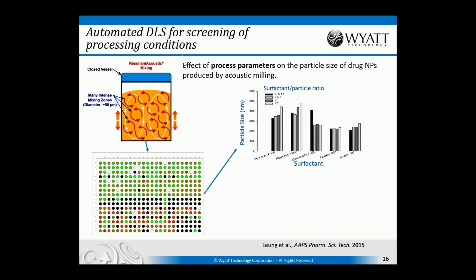This is actually done in a 96-well plate under many different energy conditions and formulation conditions, with different amounts of polymer and different buffers, to optimize the creation of these nanoparticles and their isolation by adhering the polymer to prevent the flocculation. Periodically, they would pipette some of the material out of the 96-well plate into a 384-well plate, which was then put into the DynaPro plate reader to assess formulation conditions. And they were able then to quite automatically determine the particle size as a function of the surfactant, which was used to prevent the aggregation,